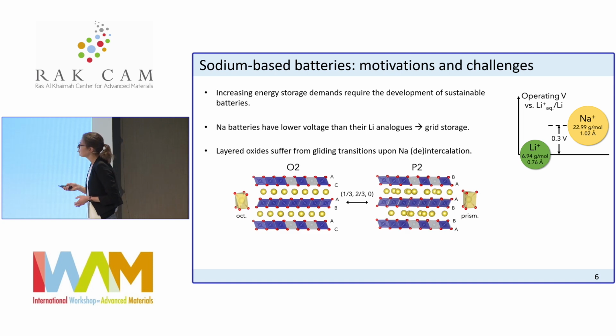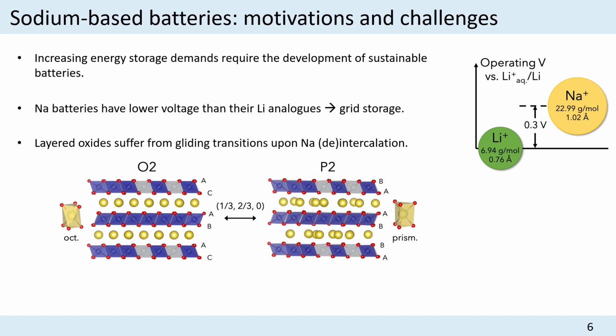So I will talk a bit about cathodes in this talk, and the reason why we're looking at new materials is because lithium-ion batteries, when you have a lithium-ion cathode that's commercialized, it's typically a layered transition metal oxide. So you have these kind of layered structures where you have layers of transition metals, and in between the layers you can insert and extract lithium. For sodium, that type of material doesn't work as well because you have many phase transitions as you try to extract and reinsert sodium. And these phase transitions are not reversible or only partially reversible. And so really my group is focusing on finding crystal structures that haven't been explored for lithium, don't necessarily work for lithium, but could work for sodium.